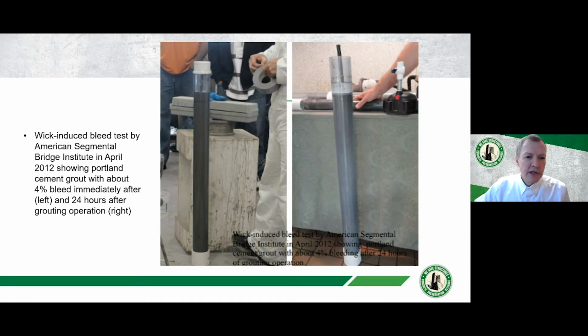The photographs that you see here are from an American Segmental Bridge Institute training session. The column on the left here was grouted with the cement water grout, and the photo on the right is the same column, with photos taken 24 hours later, and you can see that there is a height at the top that the grout level has settled. This is generally referred to as bleed. So this is the original elevation of the grout, and the grout has settled down to here.